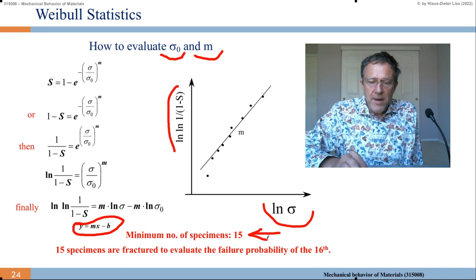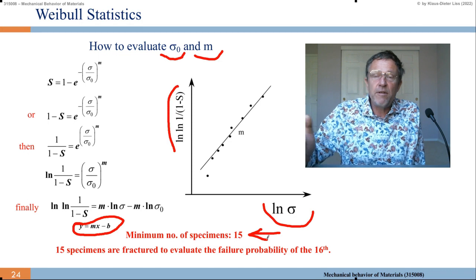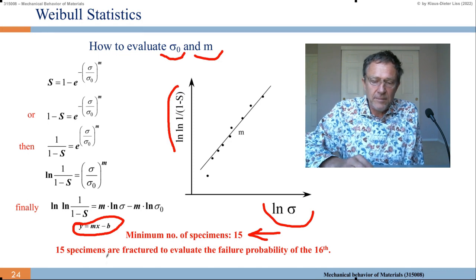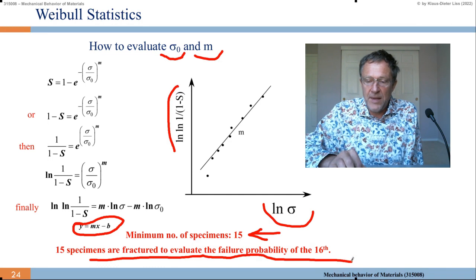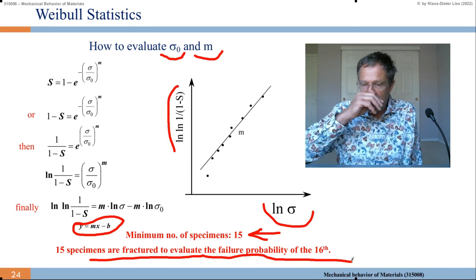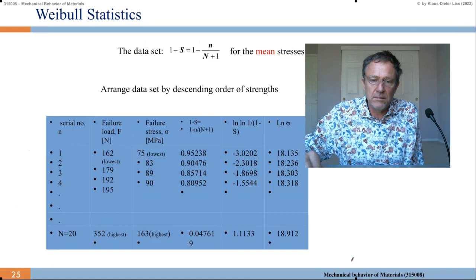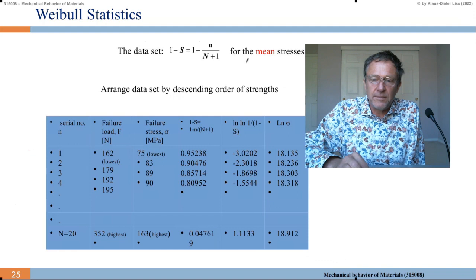And the minimum number of specimens, according to standardization, is you need 15 specimens minimal. And you fracture them to evaluate the failure probability of the 16th specimen. So you have these 15s. What's the probability of the next one? So get a data set for the mean stresses, and then you arrange the data set descending in order of strength. So you have serial numbers, you have failure load in Newton. You have the failure strength, so you have the load, you can calculate the strength by knowing the cross section, and then you put this function 1 minus n divided by n plus 1 becomes this.